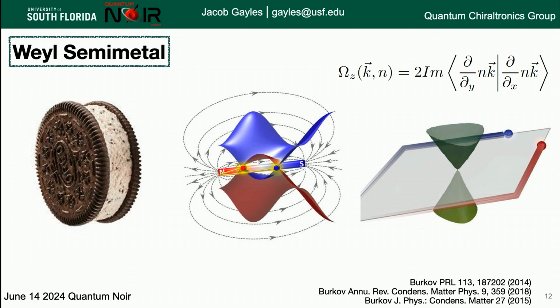What's important for the Weyl points is what's in between. What's in between there is what's called the Berry curvature, and that produces what we saw earlier, the Hall effect, but the quantum version of this was the anomalous Hall effect, and that's due to the internal magnetic field of the system. This is just a very simple picture showing this Berry curvature that comes out and how the spin of the electron changes direction upon seeing that magnetic field. So it's a spin-dependent magnetic field that comes out.